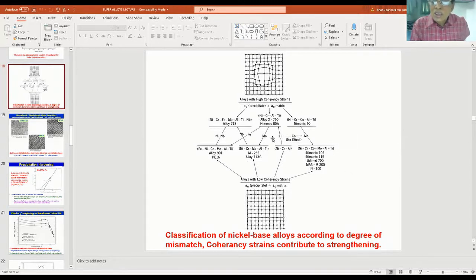So now let us see in which way they contribute to the strength. I said a lot of precipitates are forming, like gamma prime precipitate, and the matrix you have. Once you have the precipitate, it will create some strain in the matrix that will be coherent with the matrix. When the matrix and precipitate have the same lattice parameter, there will be no strain in the matrix. Some amount of distortion is induced in the matrix due to precipitation of these strengthening phases, and they induce some amount of coherency strains here.